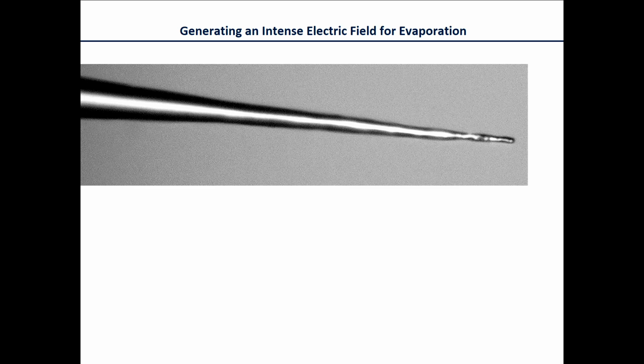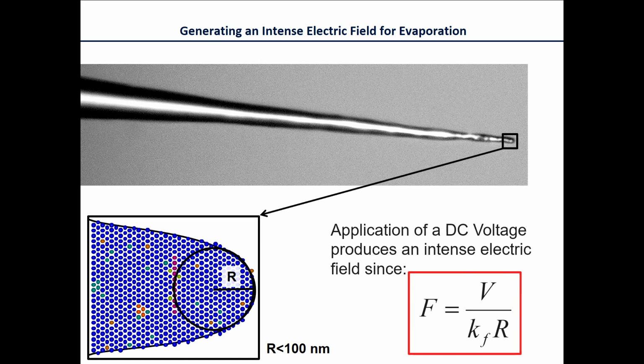In Oxford, what we do with the atom probe, actually I should say, most of this technology was invented in France, in Rouen, with Professor Blavette. The Oxford people are just kind of copying what the French people discovered. But we make a tip here, and we make this very sharp, and then we strip away the ions one by one and pass them through a time-of-flight mass spectrometer to identify which species that ion corresponds to, whether it's chromium, nickel, aluminium, and so forth.